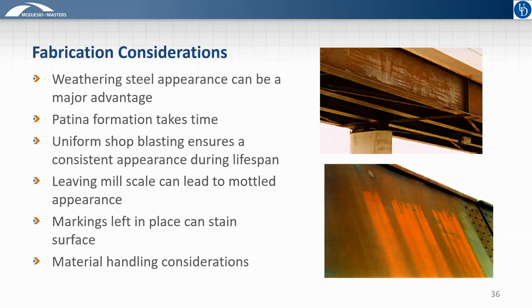The other thing to think about in fabrication is material handling. How the girders are supported in the shop and in the yard matters. If they have to remain in the yard for a long period of time, leaving them on wooden blocking can cause localized areas of discoloration. One of the best recommended practices, if you're going to have your girders in the yard for a while, is to occasionally go out and hose them down and put them through some wet and dry cycles to start the patina formation process early.